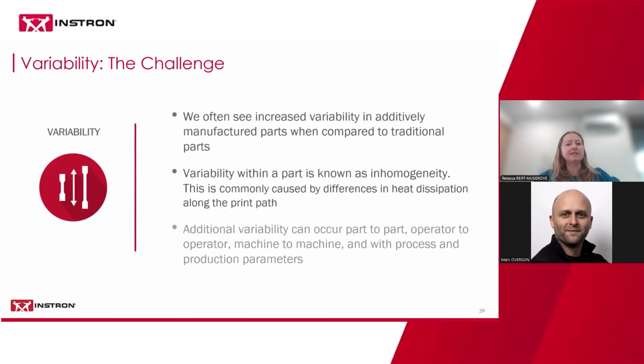So that was defects. And now I'll move on to variability. So the challenge with additively manufactured materials is we often see increased variability when we compare them to their traditional parts, in part due to those defects we just mentioned and how it's not always certain exactly where and when you'll see those defects. So we get variability within a part, and this is known in the materials world as inhomogeneity, and that can be due to differences in heat dissipation along the print path.